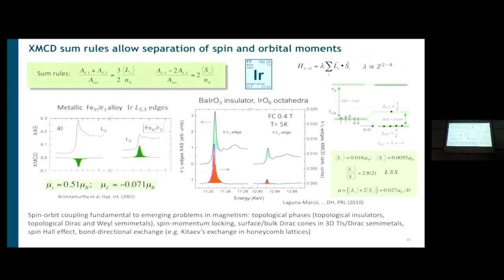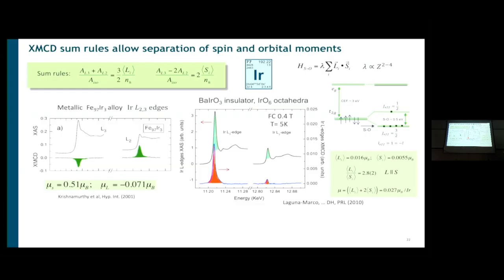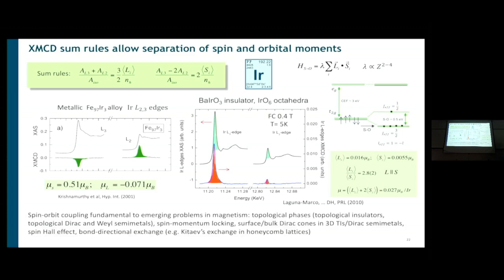And you're doing it on the atoms of iridium? Yes, we are resonating. You can do it on any atom, so you can do it on iron, you can do it on cobalt, you can do it on iridium, you can do it on any suitable resonance. I see. With large spin-orbit coupling. Well, you want to find out, is spin-orbit coupling active and present? And then you go, okay, I'm going to measure this XMCD at these 2 spin-orbit split edges, and I can apply the sum rules. The one limitation is that this is for 3D, 4D, 5D systems. Okay, so first, second, and third row. For rare earths and other elements, the sum rules become very complicated, and it's not so easy to separate.